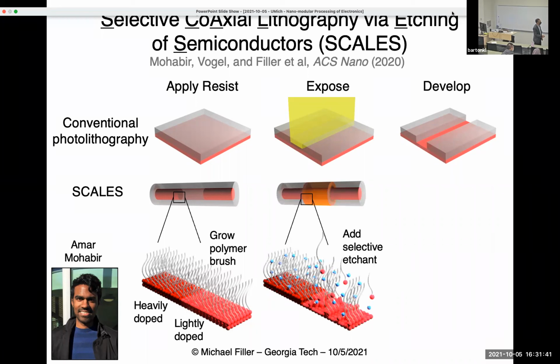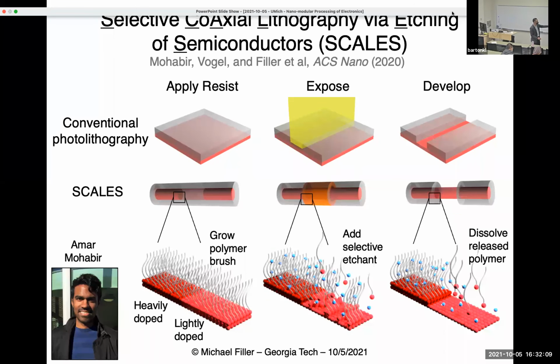And then we have a selective etchant that diffuses through the polymer and attacks the silicon on the nanowire. And a lot like a plant in a pot, if you hold the plant, which is the polymer in this case, and you sweep away the soil in the pot, which is the silicon, the plant comes out really easily. So that's exactly what's happening here, is that the polymer gets released when you etch a little bit of the underlying silicon. And if you keep going and you design this process right, you should have polymer remaining on the regions that don't etch and have it removed entirely from the regions that do etch.